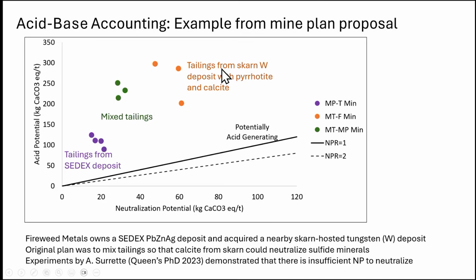Here are tailings from the skarn tungsten deposit. Yes, it has a lot of calcite, but it also has a lot of pyrrhotite, or iron sulfide. So in fact, those are also PAG materials. So if you mix them, not surprisingly, you're still above the line. So we were able to tell Fireweed that this isn't going to be a magic solution. They're going to have to think about something else, which they are.